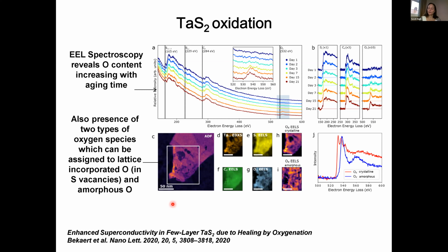That increase in oxygen was much greater in the tantalum disulfide than it was in the encapsulating graphene sheet, so it wasn't just a buildup of contamination on the surface. And by analyzing the shape of that oxygen K-edge, we were able to separate the fact that you had both an oxygen component, which was crystalline, and an oxygen component that was amorphous. So the presence of a crystalline oxygen component really does suggest that that oxygen was indeed substituting into the lattice and is in agreement with the theory.